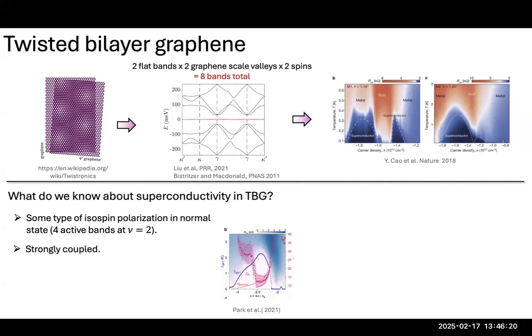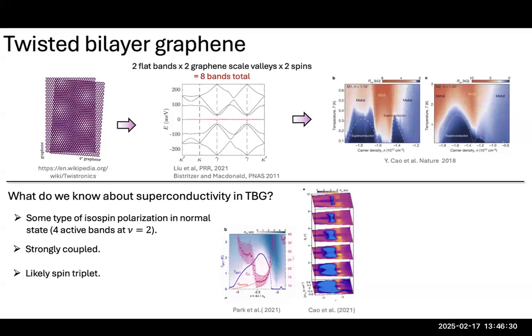We also know from measurements of the coherence length in the bilayer system that superconductivity is thought to be very strongly coupled. And also from the bilayer system, they measured the superconductor in an in-plane magnetic field, and they find it survives up to fields, I think, roughly 2 to 3 times in excess of the Pauli limit. So this is evidence for spin triplet superconductivity.